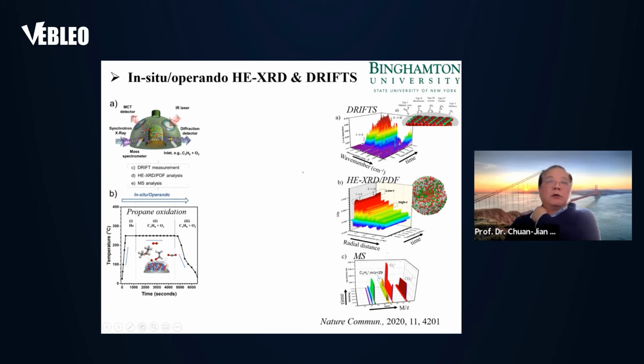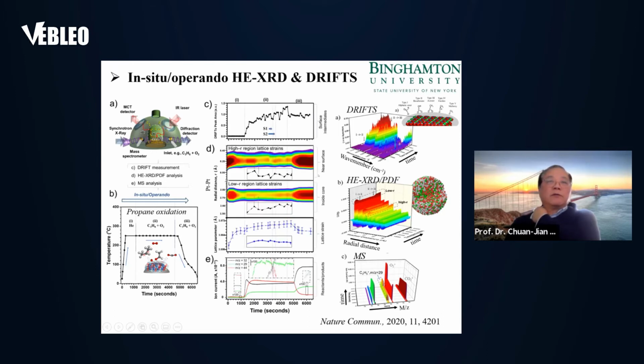So I really want to narrow the focus to the middle panel. It's really the major result, showing at the top that the detected surface species actually increase as a function of time during the reaction.